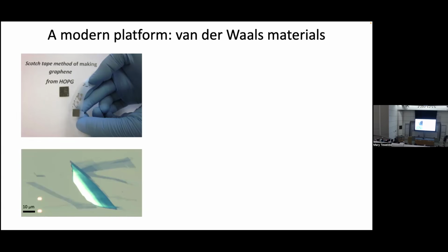This is a picture from my PhD days, actually. It's a picture of graphene and bilayer graphene and thicker graphite. And it turns out that just with an optical microscope, you can distinguish what is a monolayer of graphene, which is typically the very thinnest thing that you see on the substrate, and what is a bilayer. So this is an example of a bilayer, and you can very easily tell them apart, even though the layers themselves are just one atom thick.